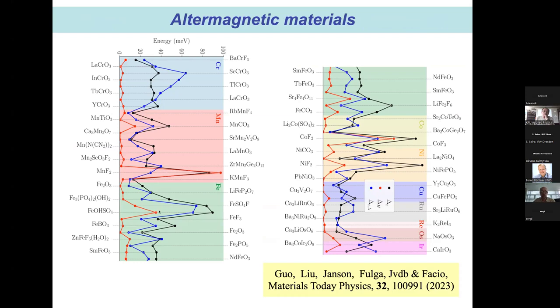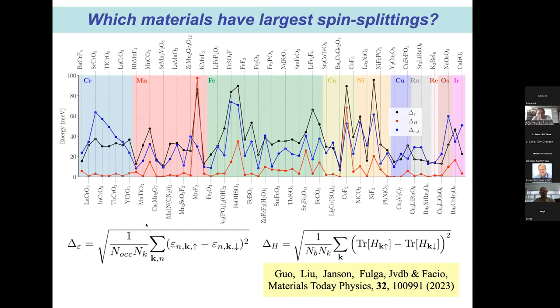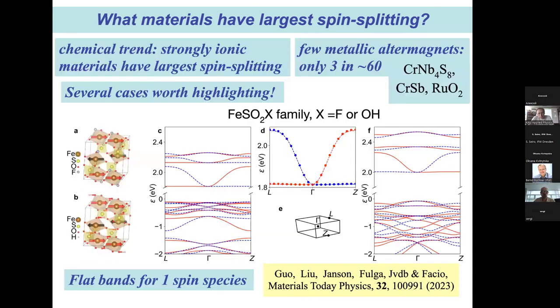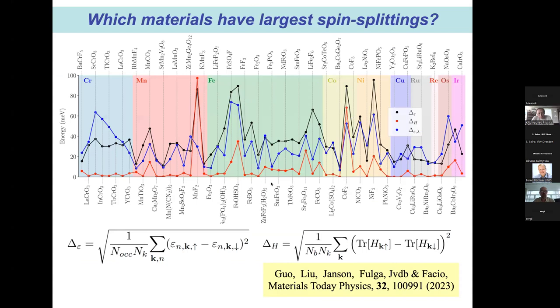So these are now materials. And what we plotted here in red, blue, and black are curves that are quantifiers for the spin splitting. Materials that you see are manganese fluoride, for instance, nickel fluoride, which are systems with the rutile structure. Cobalt difluoride also has a rutile structure. These are the two different measures of the spin splitting that we defined. And now if you look, for instance, at cobalt difluoride, you see that by all measures that we defined, it has a large spin splitting.